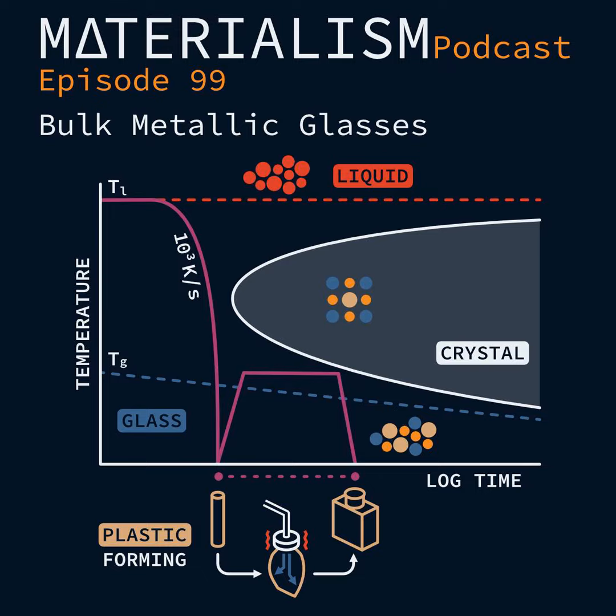So this makes sense. Here you have a mixture of gold and silicon, the eutectic is probably 20% or something like that. And then all of a sudden at a low temperature, so diffusion's not going to be very high, you have to somehow eject out all the silicon and all the gold to separate regions. And that would give you the eutectic structure. But that takes diffusion. And if this is happening so fast at such a low temperature, it just won't happen. And so you're left with this frozen structure.